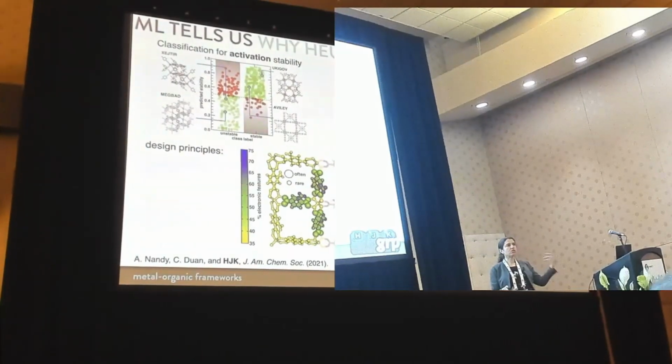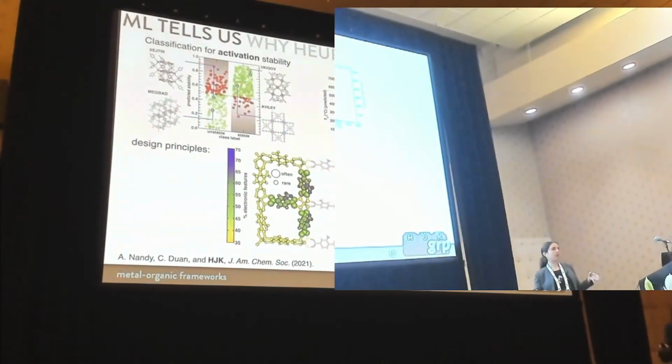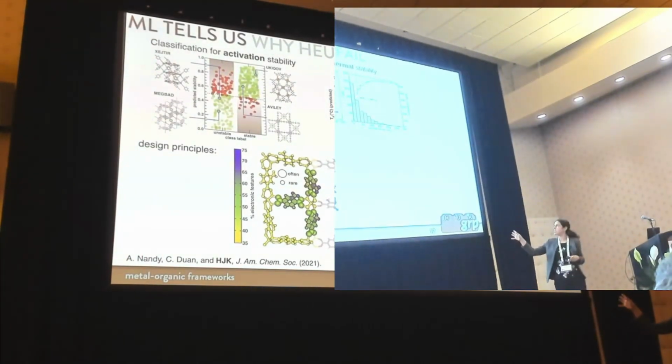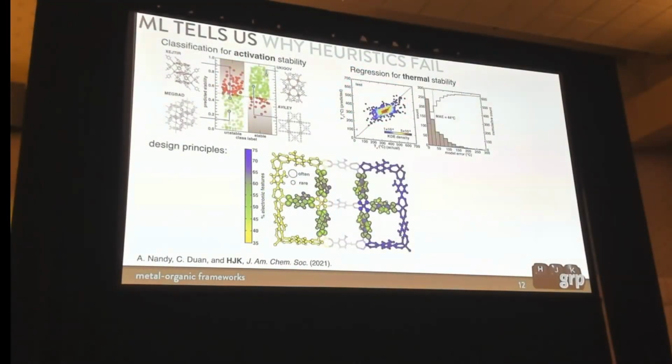The same thing goes for thermal stability. Thermal stability from the TGA is inherently noisy. We know that there is uncertainty in the measurement, and not only that, there's uncertainty in the reporting of the decomposition temperature. We sidestep that by digitizing the TGA curves, and so we use systematic information. But even then, you see the accuracy is just okay. Pretty okay, but it's better than what we could ever get from simulation information. And again, linker chemistry really dominates, along with the electronic properties of the linker.